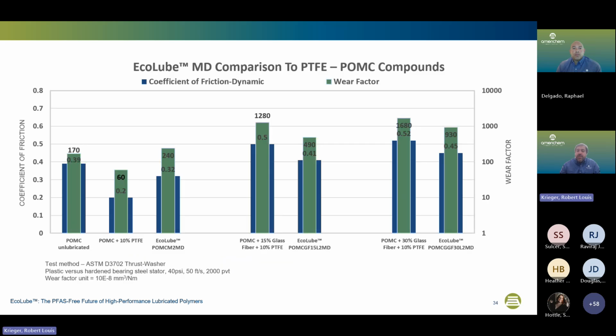And lastly, in POMC polymer, so unfilled, 15% glass filled, 30% glass filled. We see great results, especially in the glass filled grades here.